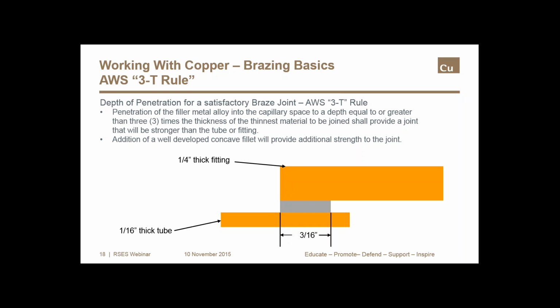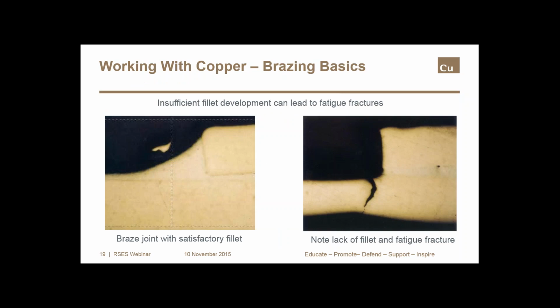A continuous fillet of filler metal should be visible completely around the joint, as illustrated here. The photo on the left shows how the fillet covers the heat-affected zone from the brazing process. In the photo on the right, we see a joint without a fillet and a fracture just outside of the joint. And that fracture is in the exact location where the fillet would normally be to strengthen this area.